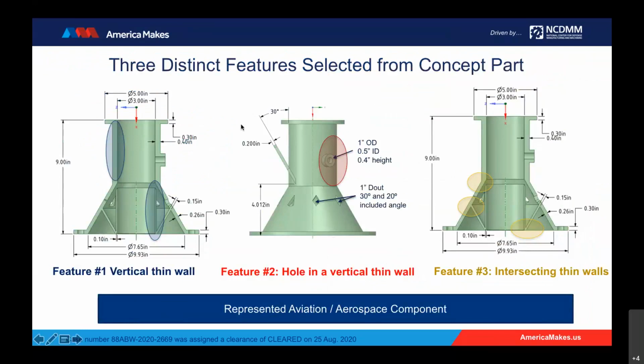The chart you can see here shows the different features of interest. The first feature, the most simplistic of them, is the thin vertical wall feature highlighted in blue. Features 2 and 3 are really variants of feature 1, where we have discontinuities or intersections of thin wall structures. Feature 2, the one highlighted in red here, is a hole. We cannot build it by vertical build orientation, so you have to change the build itself. But for other builds like rhombuses and the teardrops, the ones you see at the bottom, you can build with a single build orientation. So we chose those as the hole geometry of choice.